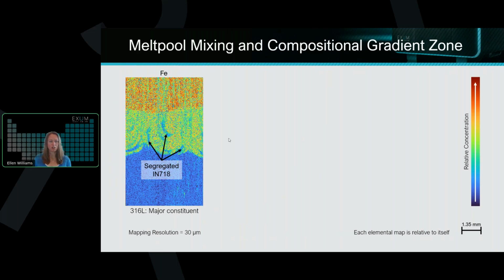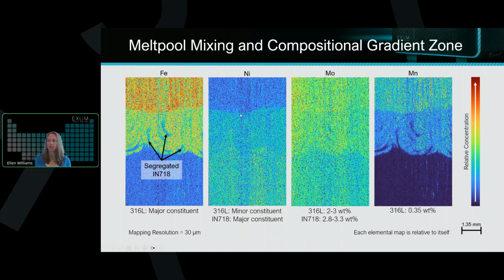So the next slide here, I'll just show you what some of the other elements look like. Again, we've got our iron map, and then the same area, we're looking at the nickel, where you see much less of a stark gradient, because nickel is the bottom layer, and then as the steel is solidifying above it, we get less of a stark gradient in that melt pool. But those areas where we see low iron is exactly where we're seeing some of those yellow and green on the nickel map, where we're getting some of that nickel alloy mixing into the iron